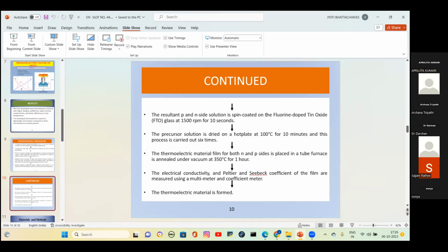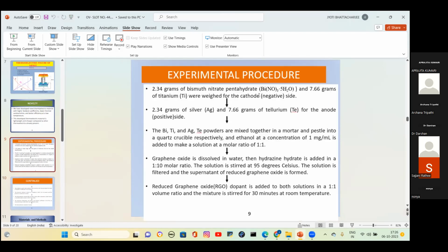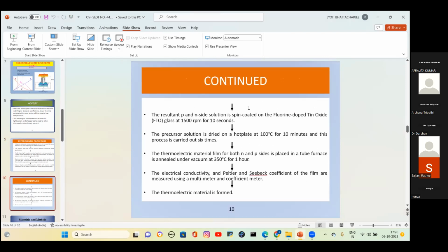On this fluorine doped tin oxide that I have used as a substrate, I have spin coated the P side and N side. Firstly, for the P side, the positive side, silver telluride, I have done spin coating and then covered the P side and then I have done the N side, at 1500 RPM for 10 seconds. And the precursor solution that I have developed, I dried it on the hot plate at 100 degrees Celsius for 10 minutes and this process I have carried out 6 times.